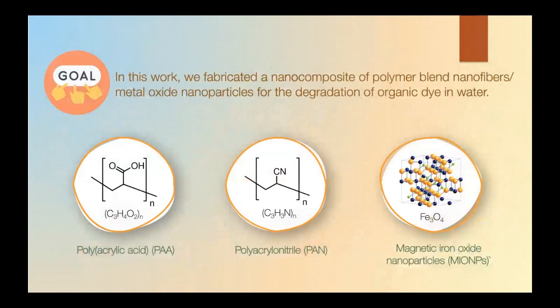In this work, we fabricated a composite of polymer blend nanofibers metal oxide nanoparticles for the degradation of organic dye in water. Here, we couple polyacrylic acid and polyacrylonitrile as nanofiber components due to their good compatibility and mechanical stability. We selected magnetic iron oxide nanoparticles due to its known photocatalytic potential. Moreover, its magnetic property offers an advantage in recovering the composite in the aqueous media conveniently.